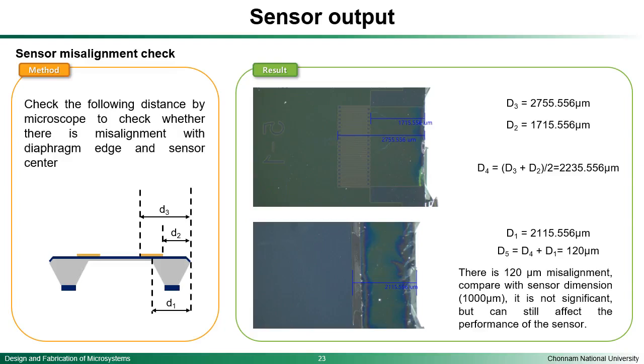Then we check D1, the distance between the diaphragm edge and the wafer edge, which is observed from the backside of the wafer. We compare D1 and D4, and we notice there is around 120 micron misalignment between the diaphragm edge and the sensor center. But compared with the whole sensor dimension, which is around 1000 microns, it is not very significant. But this misalignment will still decrease the performance of the sensor.